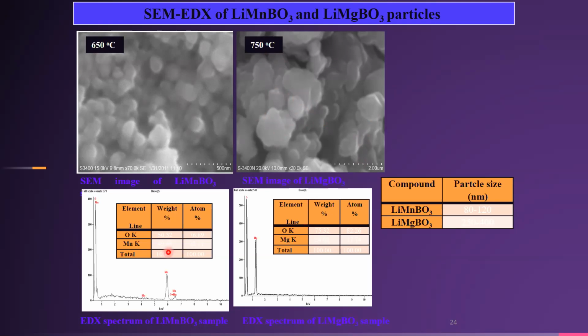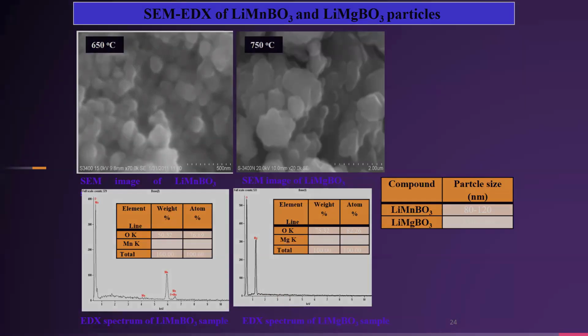The EDAX spectra of lithium manganese borate and lithium magnesium borate samples indicate the existence of manganese and oxygen in the lithium manganese borate sample, and oxygen and magnesium elements in the lithium magnesium borate sample, as obtained from the energy dispersive X-ray spectrum.